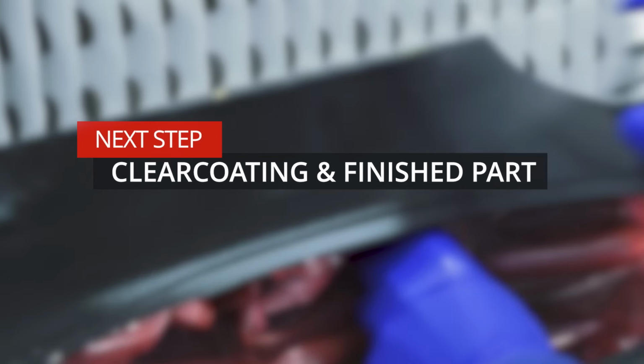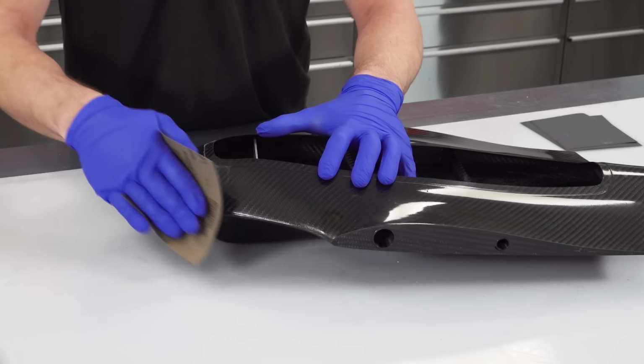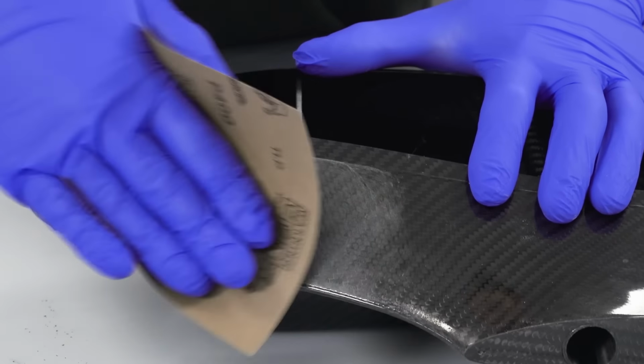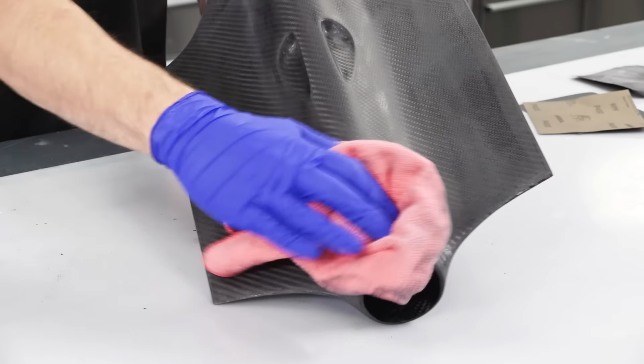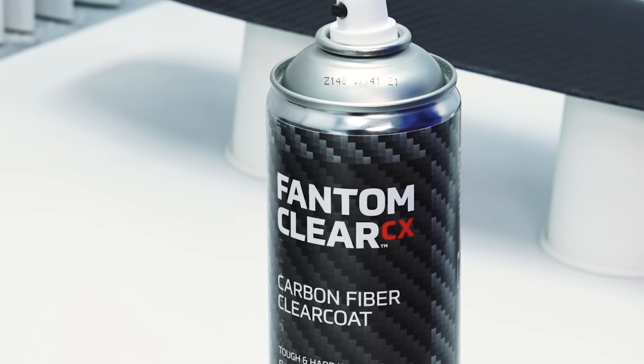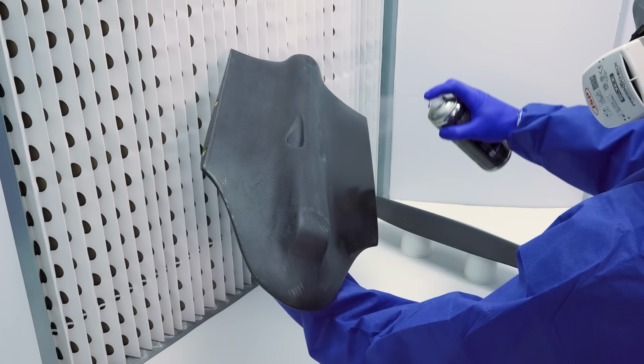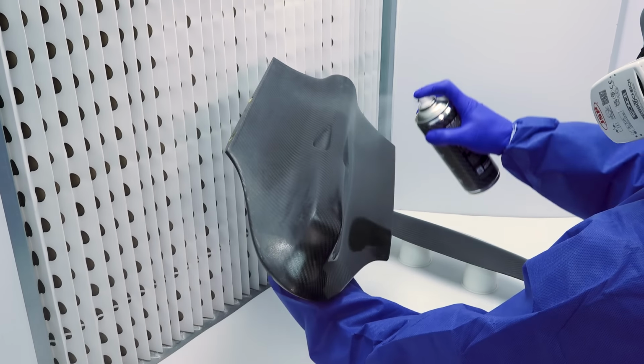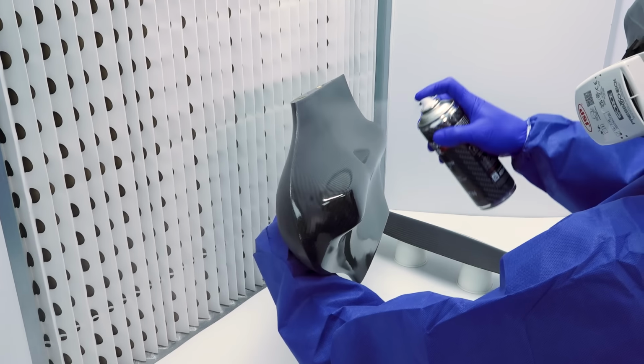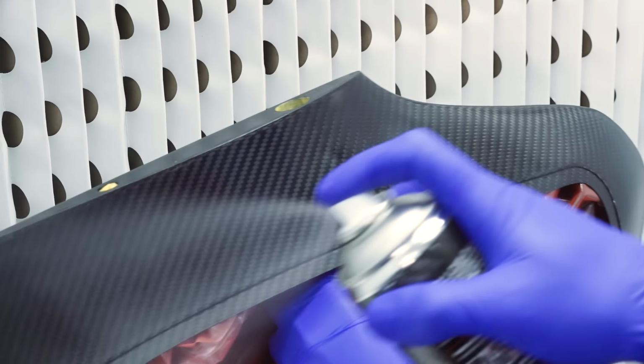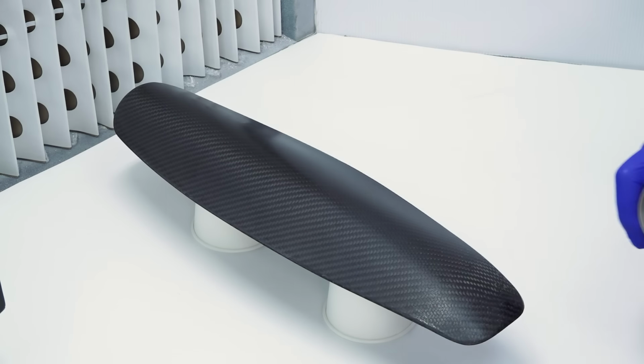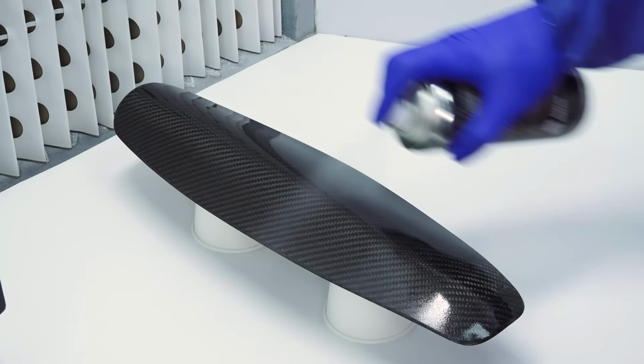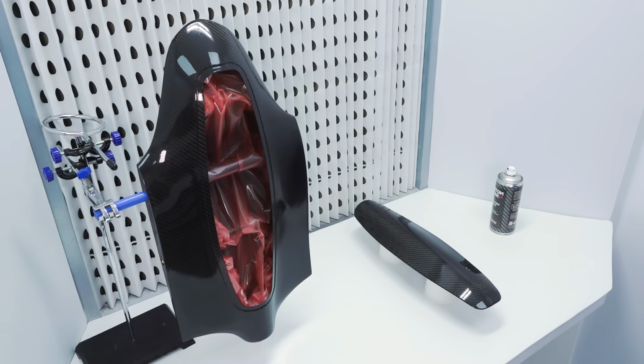With the adhesive cured, I'm now going to key the surface with 400 grit abrasive ready for paint. Typically a UAV would be painted in a solid colour, but I want to keep the carbon visible, so I'm going for a satin clear. The Fantom Clear paint I'm using here is designed specifically for carbon fibre and goes down incredibly well. High quality satin or matte finishes are slightly quicker to achieve than full gloss ones, generally requiring just a single coat, flat, then a finishing coat. Doing this did add around 10 grams to the part, but for the protection and looks, I think it's worth it.